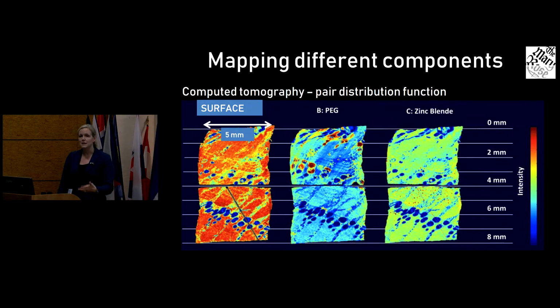And then you can isolate different phases. So what's great about this is it's telling you everything that's there. You just then have to find the match to what it is. So we knew that PEG was there, so sure enough, we can see it more near the surface and where the vessels are. We then found some really interesting things.